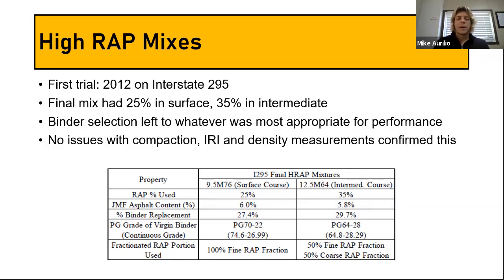Fine RAP and coarse RAP behave differently. They contribute their asphalt cement differently because of their particle sizes. The diffusion will occur at different rates. So it can impact the quality of the pavement at the end of the day if you're changing your RAP fraction size, for example.